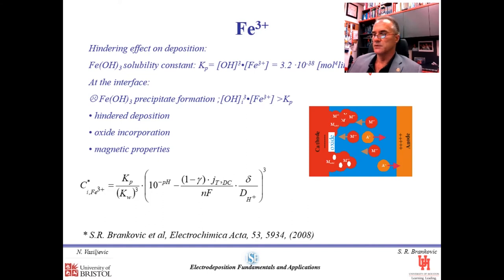Because of the evolution of hydrogen at the interface, the H plus ions are depleted, and that means that the interfacial pH could be significantly higher. Therefore, even if we have iron 3 plus in the solution, and the solution might look clean, where we don't see direct evidence of iron 3 hydroxide precipitation, the interface solution could actually behave differently. The reason is that the interfacial pH could be very much higher, and the solubility product between OH minus and iron 3 plus could be exceeded, and that's why we could have a precipitation of hydroxide at the interface while we are doing iron deposition, which typically negatively affects the metal deposit properties.